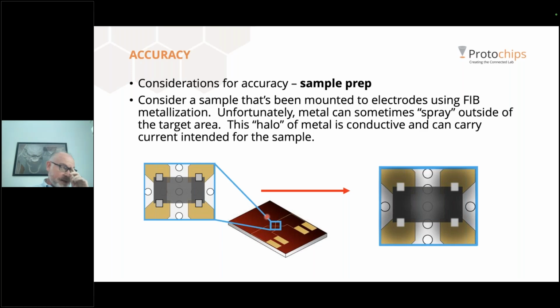Another, perhaps more important consideration is sample prep. Every sample requires some form of sample prep, and sometimes the prep itself can cause problems. For example, consider a FIB lamella that needs to be electrically connected to an E-chip. Now, one advantage of FIB is that in addition to cutting and thinning the sample, you can deposit metal onto it to form electrical connections. However, when you're trying to form several contacts within a small area, any stray metallization, like a thin halo of metal, can form electrical connections between the contacts and around the sample, right?